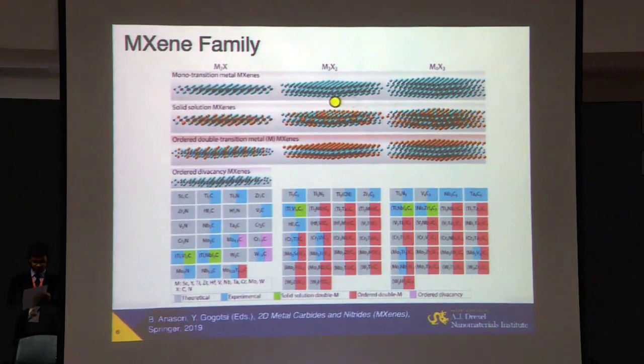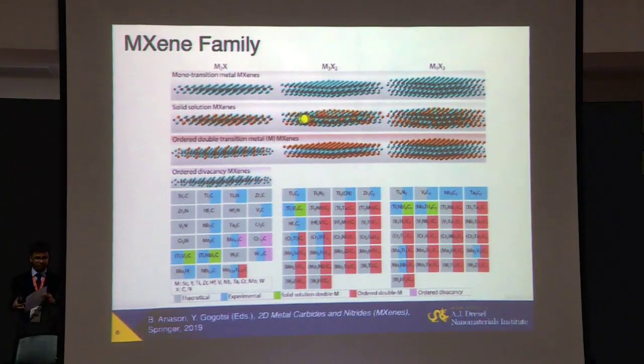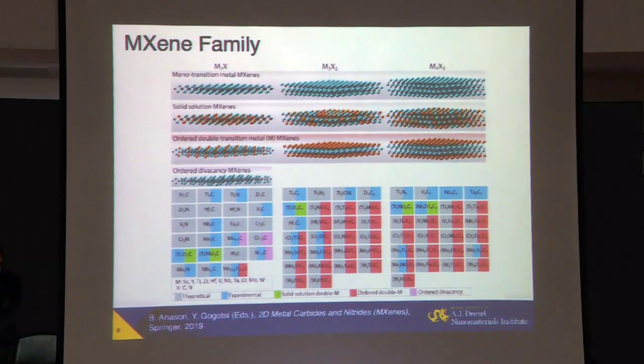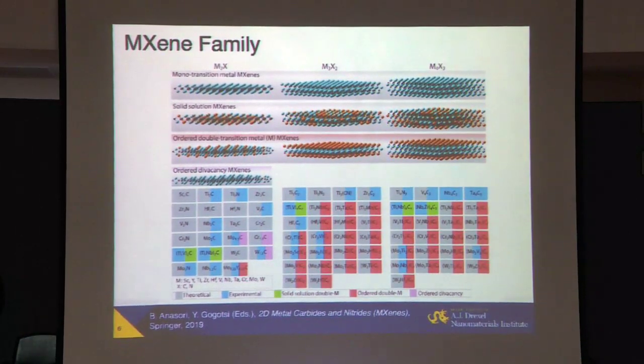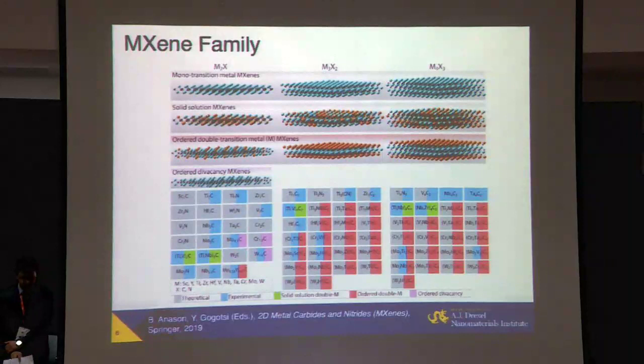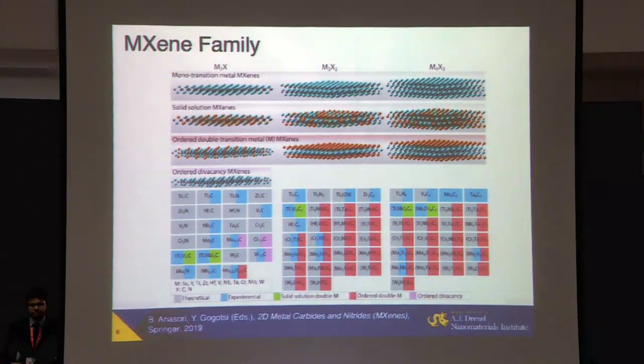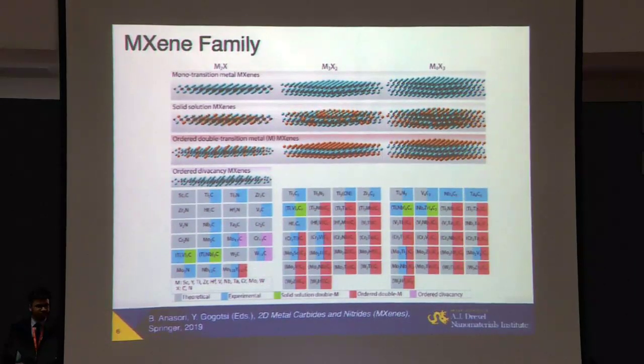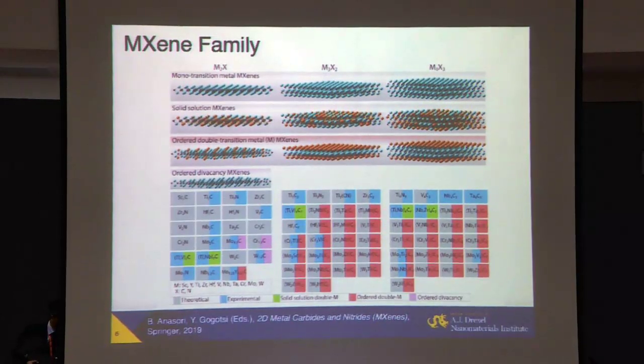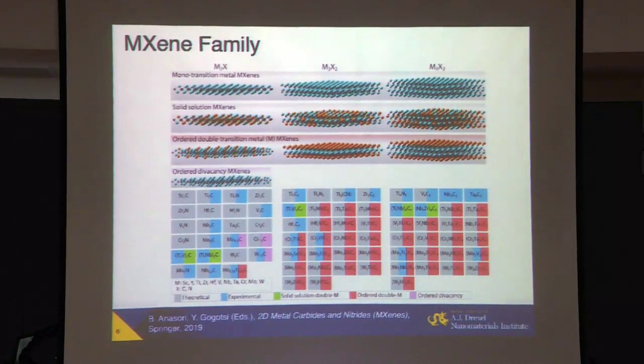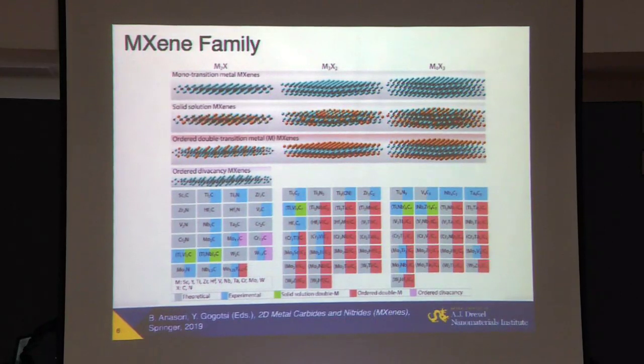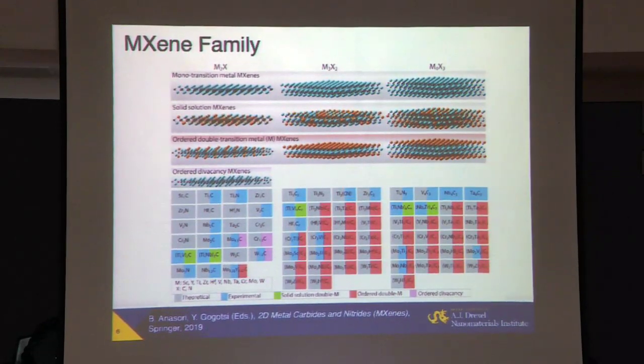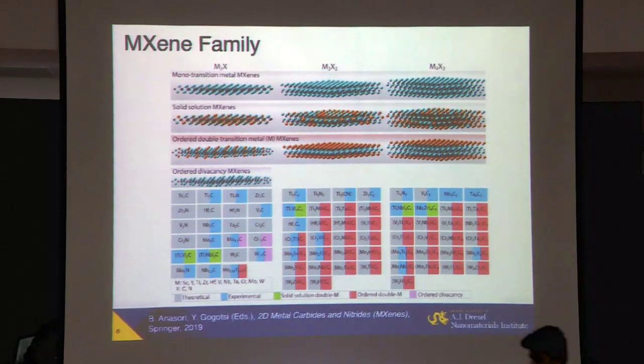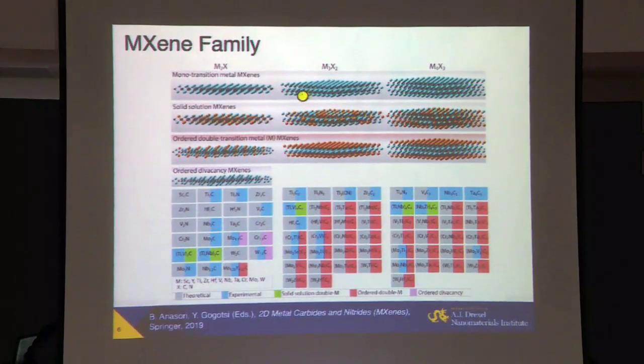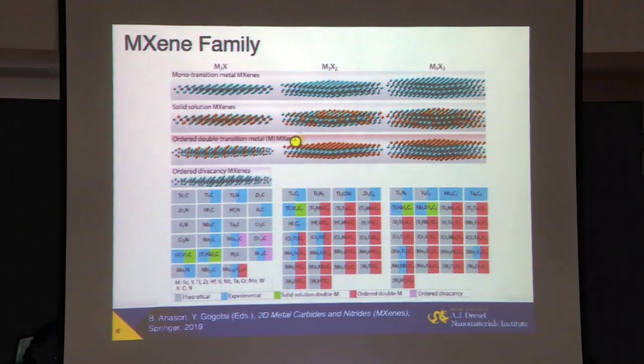But they can form solid solutions. You can actually, on the M side, mix different atoms. For example, vanadium and titanium, or molybdenum and tungsten. And they form really any number of solid solutions. So we're pretty much facing an infinite number of compositions that we can design. In my lab, I study now about 25 different solid solutions here. They also can be on the X side. We call them carbonitrides.